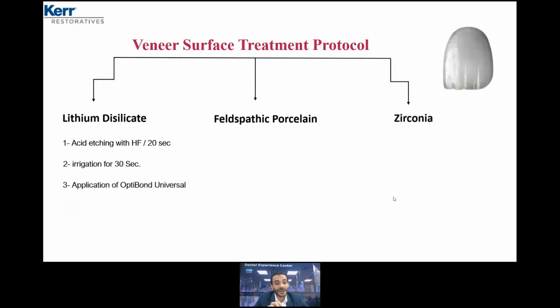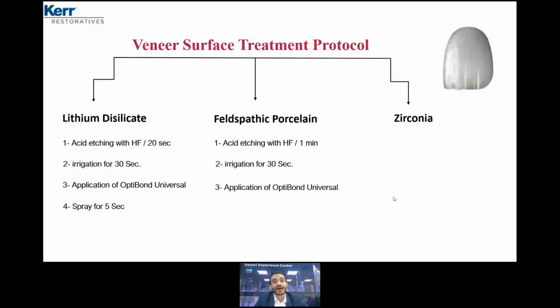Irrigation, application of the OptiBond Universal, and spray for only 5 seconds. Feldspathic porcelain, here it's not a problem. You can acid etch with hydrofluoric acid for 1 minute. Irrigation, application of OptiBond Universal, spray for 5 seconds.